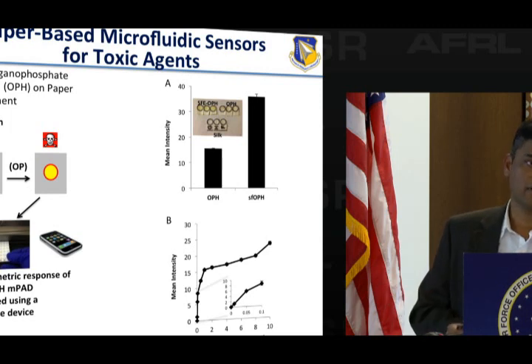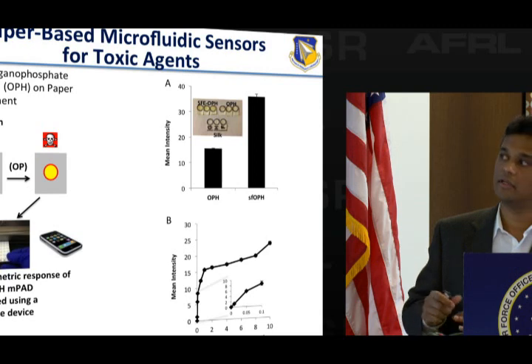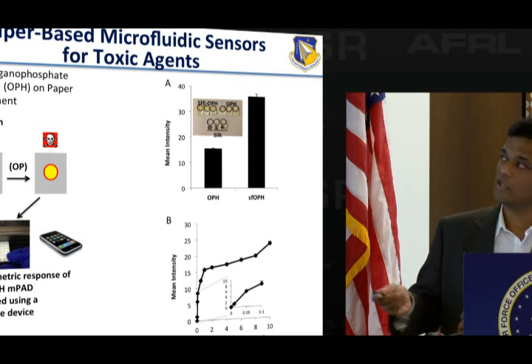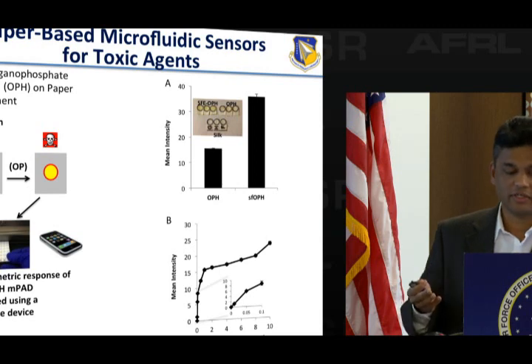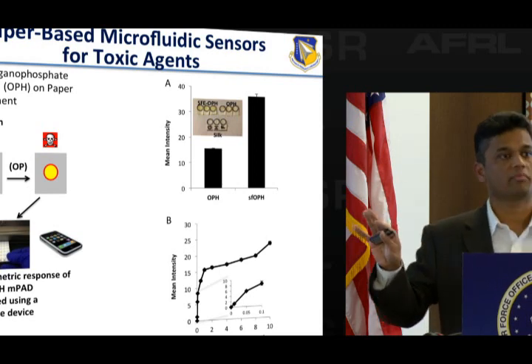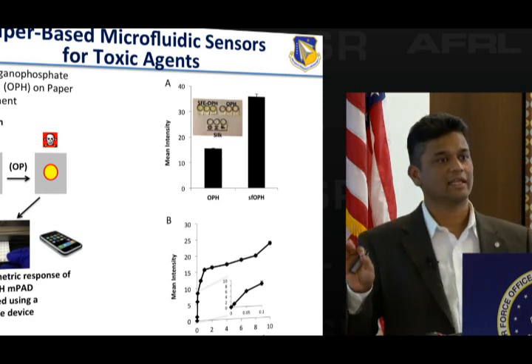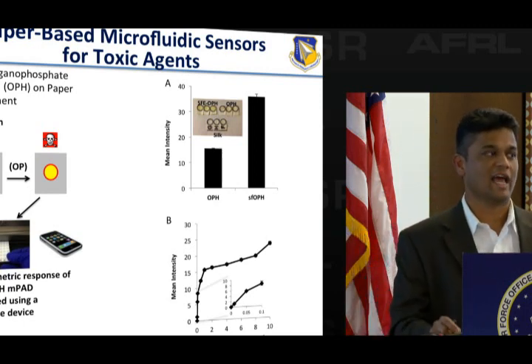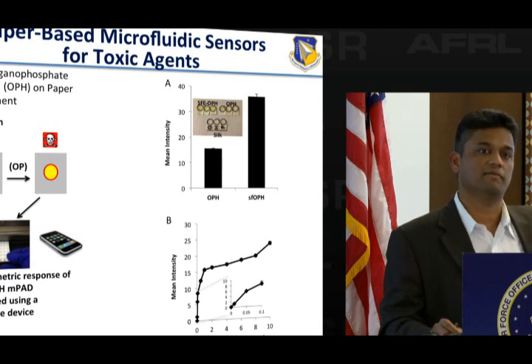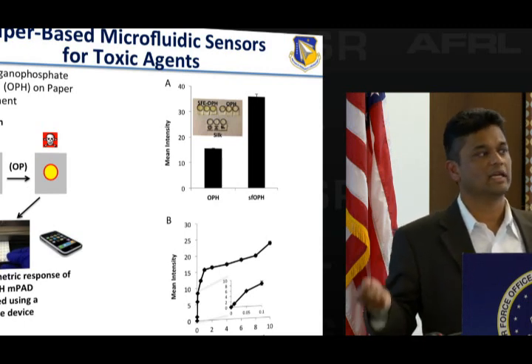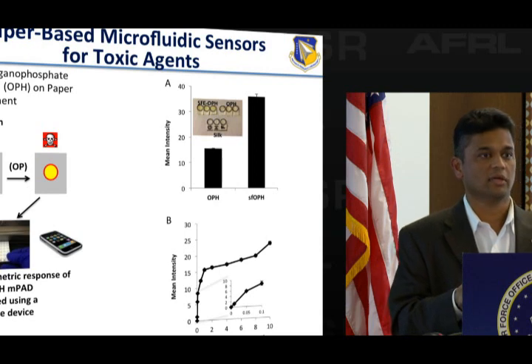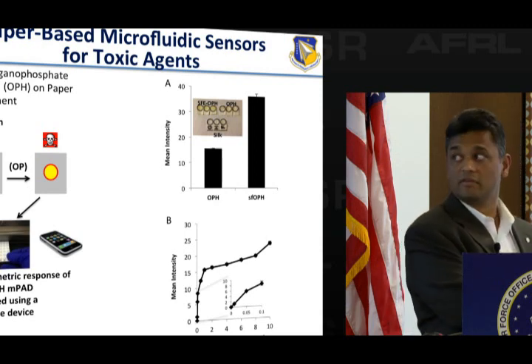So we use silk fibroin, which is a biopolymer that comes from silkworm. We have shown with David Kaplan that if you put enzymes in there, they're highly stable. They're stable against UV, detergent, and temperature. Some of the work that George Whitesides has been doing on trying to build some paper-based diagnostics, he always keeps those two reagents separate. So he just does the diagnostics at the time of the assay. So the reagents are kept in a fridge or stored separately, and then he combines the two when he wants to do the experiment. So clearly, you still have to do refrigeration. You have to preserve the biomolecule.